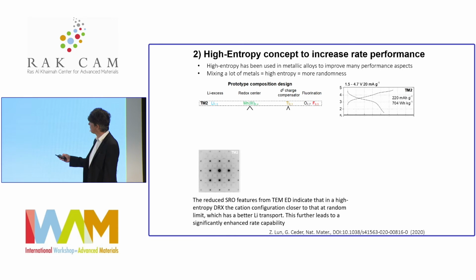So I'm first starting with materials that all have 30% lithium excess and the same anion configuration, and then I'm going to put more and more metals in. I first start with 0.4 manganese and 0.3 titanium. That gives you a lot of short range order, as you can see,